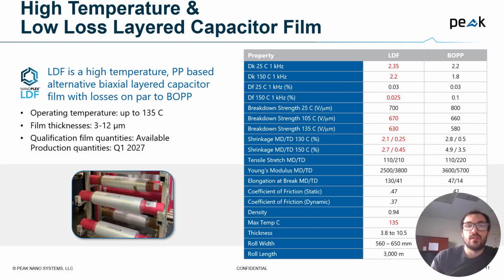And so when we compare that to Peak's product, LDF in particular, this really acts as a drop-in replacement for BOPP, but again, with this idea of really improved thermal stability, where we can sustain temperatures of up to about 135C. That's ambient temperature. It's not even hot spot. You go quite a bit hotter in terms of hot spot, actually. But what you again find is that you don't have to derate the material, and that its lifetime at high temperature is much closer to its room temperature lifetime. Again, so you gain lifetime and you gain a lack of derating.